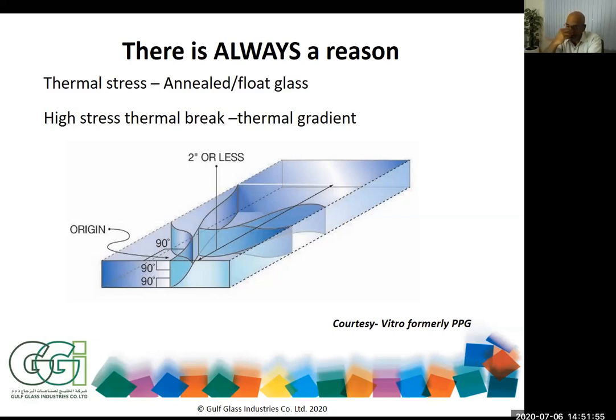Having said that, we have used annealed glass in two projects, nearly 60,000 square meters of annealed laminated glasses. It's been nearly 10 years that the project is in service, and we do not have any thermal stress breakages. The outer glass, to be precise, was a heat strengthened, high performance, double silver glass. So, if the thermal stress analysis has been done correctly, you can use annealed glass on buildings. And this is used in the Middle East. And it is perfectly okay.